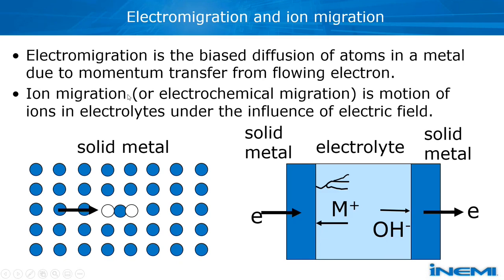In the case of ion migration, which is also electrochemical migration, this happens in between two metals which are connected, which are bridged by an electrolyte. So let's suppose you have two copper metallizations on a circuit board, and you have contamination in between, and this contamination is ionic. So because of potential, the metal ions can dissolve into the electrolyte, and there's moisture there.